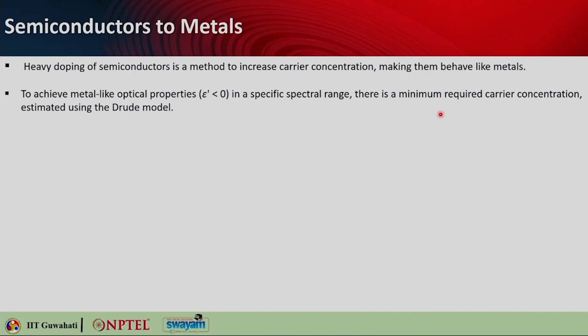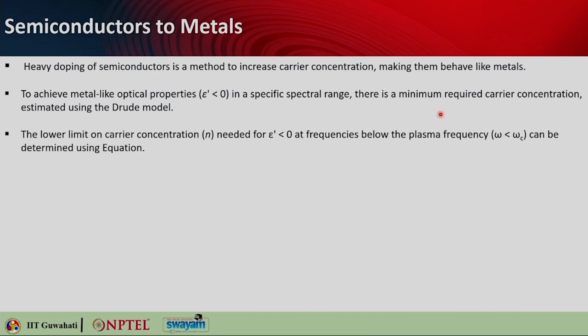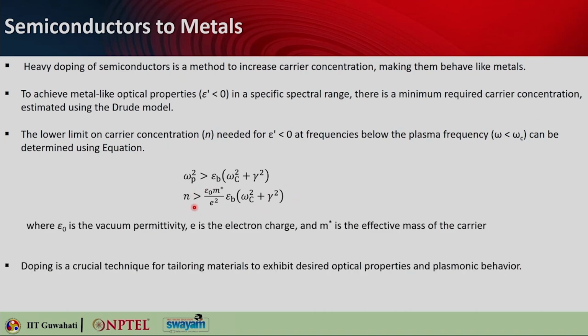There is a minimum required carrier concentration that can be estimated from the Drude model. So, you have to make sure that you reach that level. The lower limit on n for achieving negative permittivity at frequencies below the plasma frequency can be taken from this equation. So, omega p square should be greater than omega c square plus gamma square, where n will be greater than this. So, you have got a limitation. This has a lower limit that will give you a negative real part of the permittivity at frequencies below the plasma frequency. So, you are looking for omega less than omega c. This is basically the crossover frequency omega c.